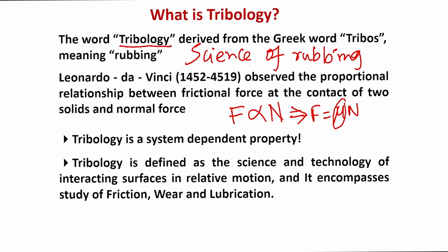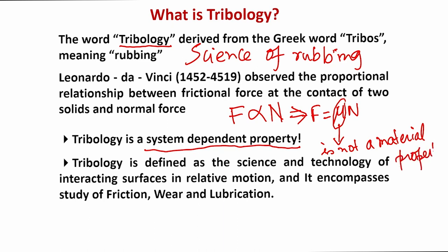One of the main things in tribology that all researchers should always remember: tribology is a system-dependent property. Friction of stainless steel does not mean anything unless one asks what is the friction coefficient of stainless steel against alumina, or against aluminum alloys, for example. The friction coefficient μ is not a material property — it is a system property. Therefore, one always has to identify what is the mating solid.